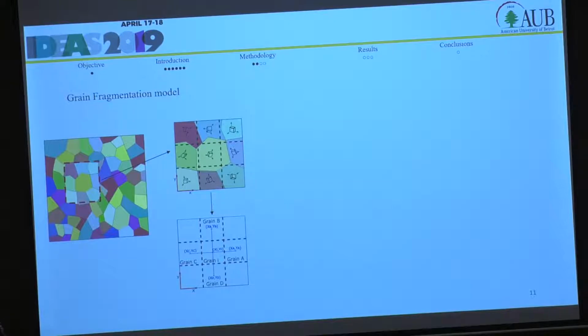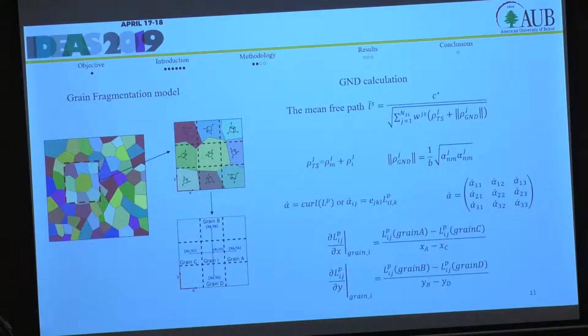So in order to implement the grain-grain interaction, which will affect our fragmentation process, a concept called the GND, or the geometrically necessary dislocations, is used. These dislocations are accommodated at the grain boundaries. So we'll have on the grain boundaries geometrically necessary dislocations that will hinder the rotation of the boundary during deformation.